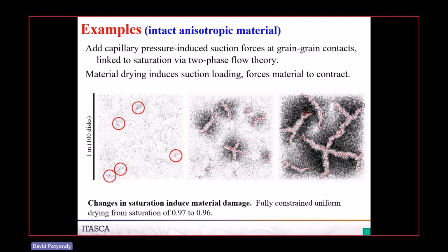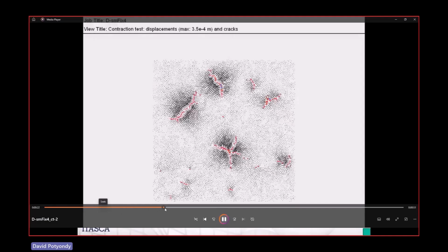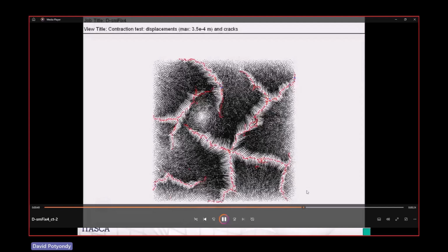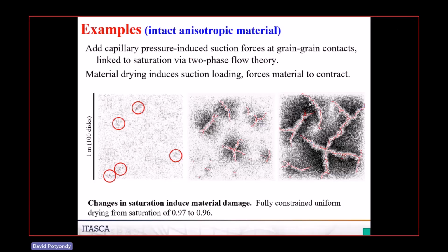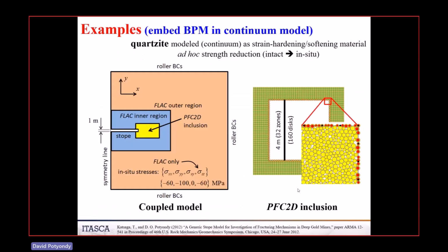As we take a system at saturation of 0.97 and reduce the saturation a little bit, that increases the suction. And what you then see is this evolution where it begins to fail at these tensile breakages, and the boundary condition is fully fixed all around the boundary. So you've got this shrinking material fully fixed on the boundary. It's sucking itself in, and that localizes, and then those localizations grow and eventually go across the whole thing. This is similar to desiccation cracking of a clay. If I speed things up, you can see they're initiating, then they're interacting, and they're forming something like this. So that was some work showing the addition of a saturation concept to an unsaturated material.